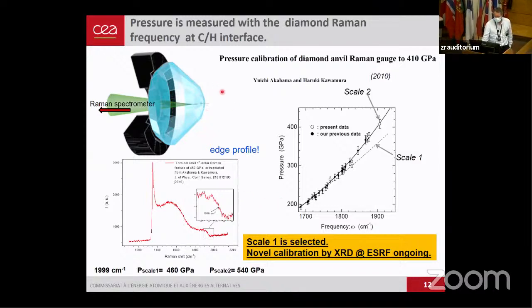So there has been a scale that has been proposed by measuring the Raman phonon of the diamond at the interface with the sample. And so diamond has a strong phonon mode at 1333 wave numbers. And then if you do the Raman measurements through the diamonds, you see that you are really crossing all the pressure range until you reach the highest pressure at the tip. And so you have this kind of spectra where you have flat and then the small steps and then the distribution of pressure in the sample. And really you have to measure this edge, the frequency of this edge.